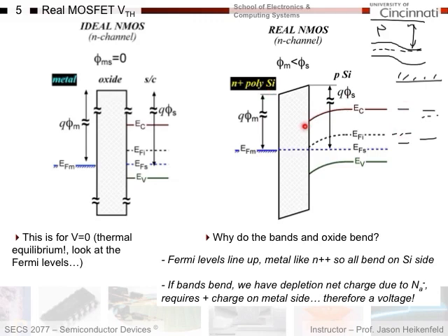All the band bending occurs on the oxide and the lightly doped side. So this is so heavily doped that you assume there's no band bending here. Again, we treat it like a metal, essentially. The other thing that's interesting to know here is that as soon as you see this happen, you know that when I get the band bending, holes drift out here, right? And so that means I've got some net negative charge here, right?